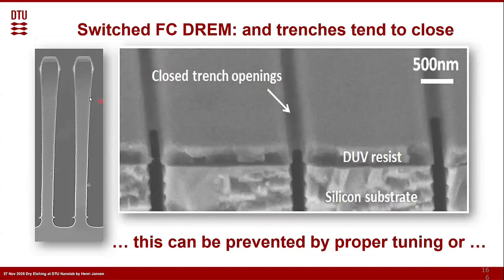But there's something else that is going to happen, and that is there's fluorocarbon deposition all the time. So every step we do a fluorocarbon deposition, and I said before already, at the top side it can tend to be depositing more than at the bottom. So at the bottom we would like to have still a good enough passivation, but that means we more or less overreact at the top. And you can see here that the fluorocarbon is slowly coming together. And when they have a very small structure, like here, they can even start to close the trench. So, of course, you can try to do that by proper tuning and saying, okay, I'm going to do a little bit less in the end, etc. But there's a lot of compromises then.